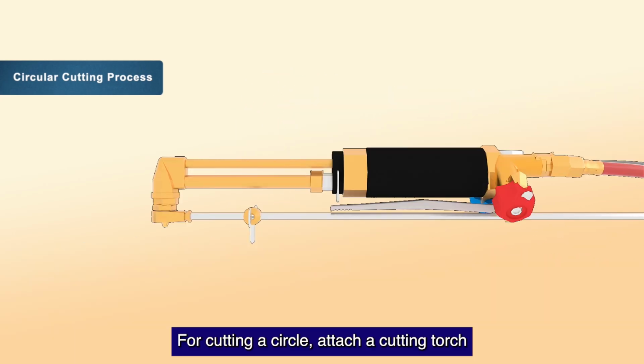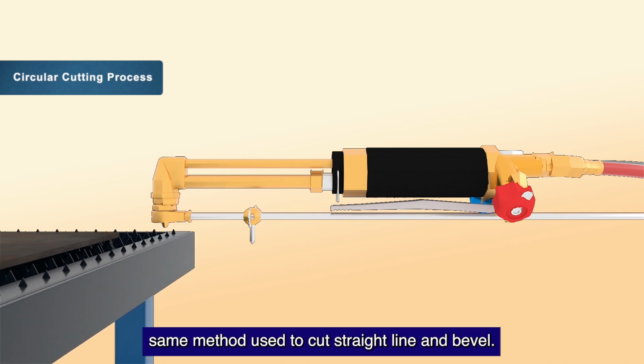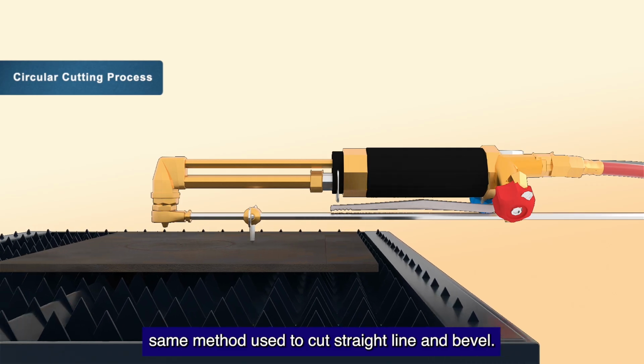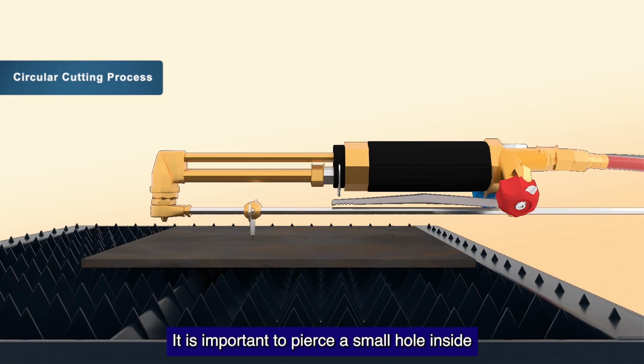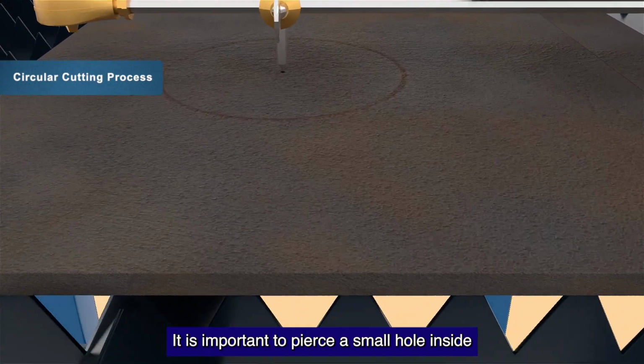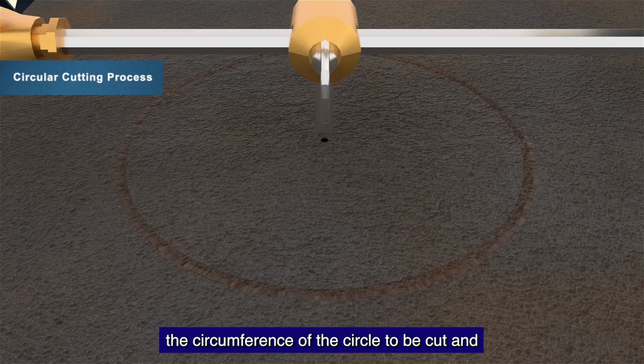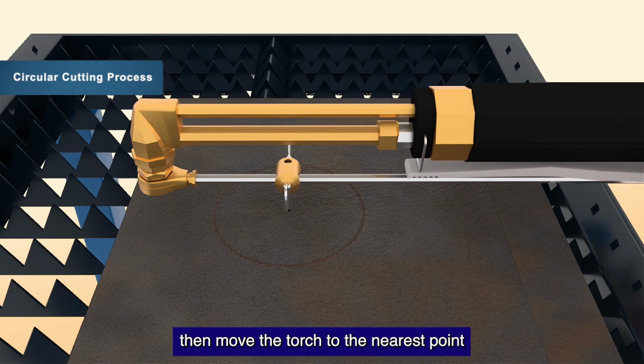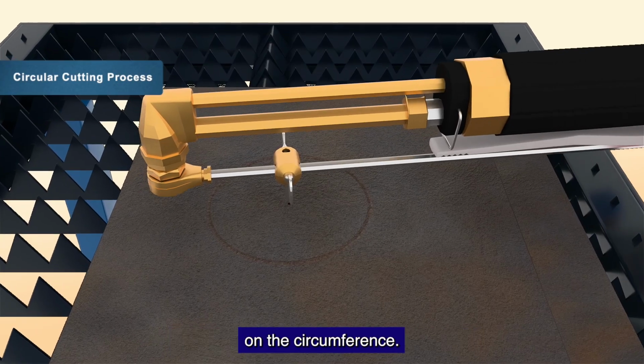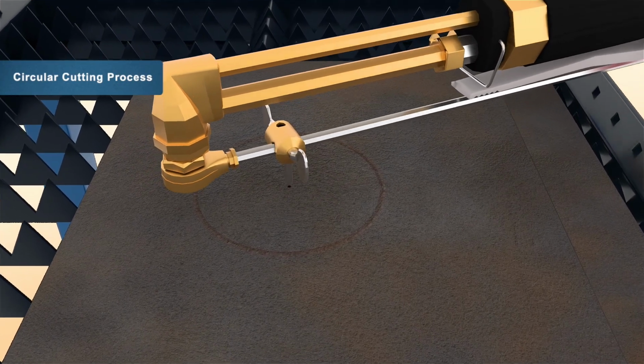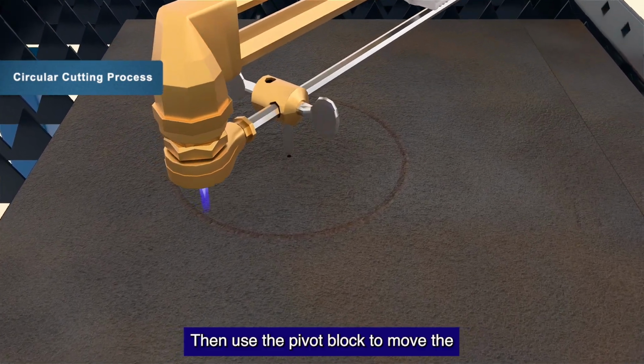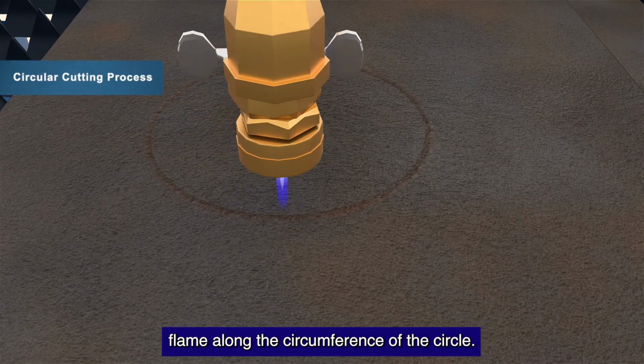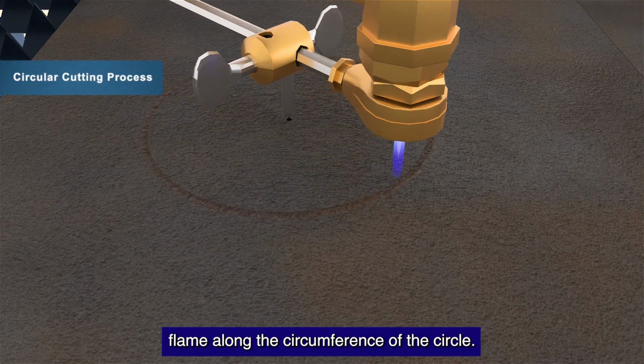For cutting a circle, attach a cutting torch nozzle to the pivot block and follow the same method used to cut a straight line and bevel. It is important to pierce a small hole inside the circumference of the circle to be cut, and then move the torch to the nearest point on the circumference. Then use the pivot block to move the flame along the circumference of the circle.